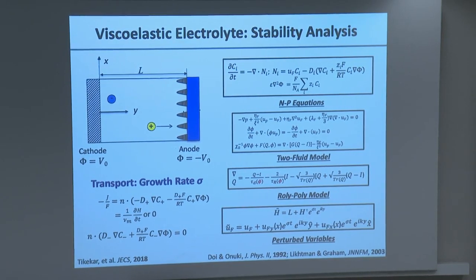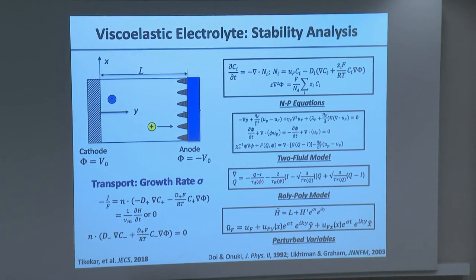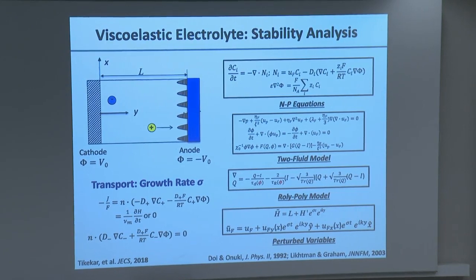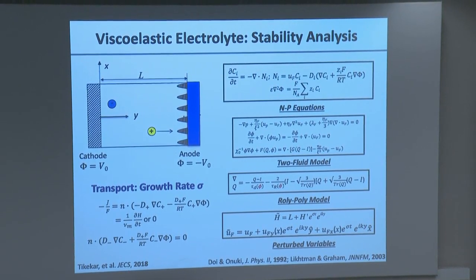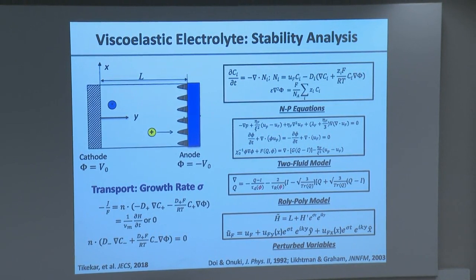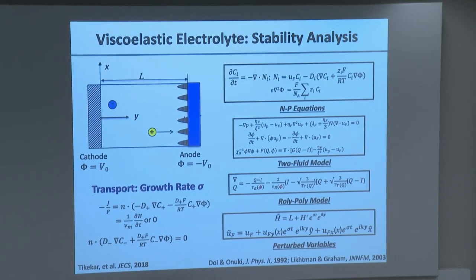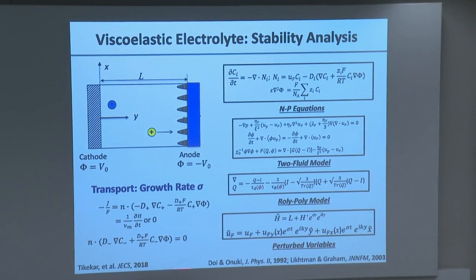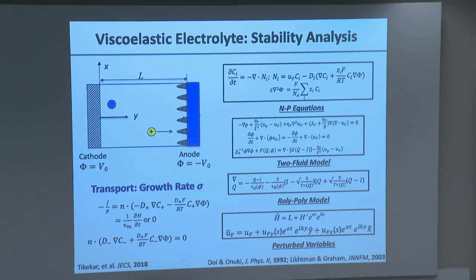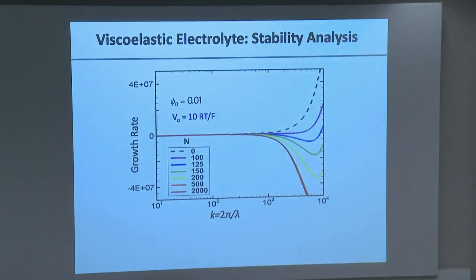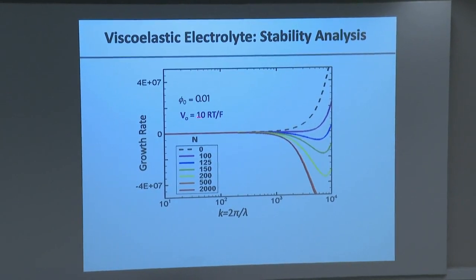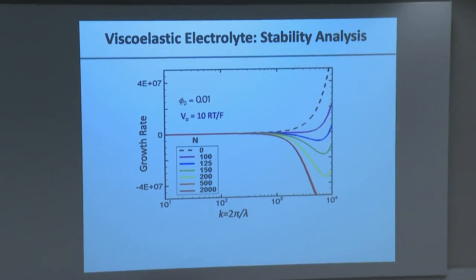And then we did what's called linear stability analysis. And so the idea is that we perturb the surface. We say, what if bumps form? Well, obviously, if bumps form, they change the boundary conditions the fluid experiences, and that then propagates through all the equations, all the variables. And the question was, if we then enforce the boundary conditions that the negative ions cannot penetrate through the interface, and the positive ions deposit at the interface to produce a current, we can then figure out what the growth rate is of these bumps. That is a mouthful. The answer is nicer, cleaner. So what we can do is actually plot that growth rate for a fixed polymer concentration, 0.01, so that's 1%, at a fixed potential, so this potential is 10 times the critical potential where the current approaches the limiting value.